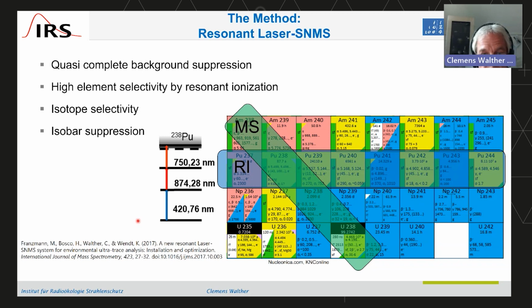And how do you do that? If you picture just the neutral atoms, you fire at these atoms with the laser, and you do it in a resonant 3-step excitation scheme. So here is the atom, and then you excite an electron in 1, 2, 3 steps, and then it is excited to exceed the ionization energy, and then you produce plutonium-238 ions. So it is a selective ionization of just one element, and that gives you a very high element selectivity, and together with the mass spectrometry, it gives you an isotope selectivity.